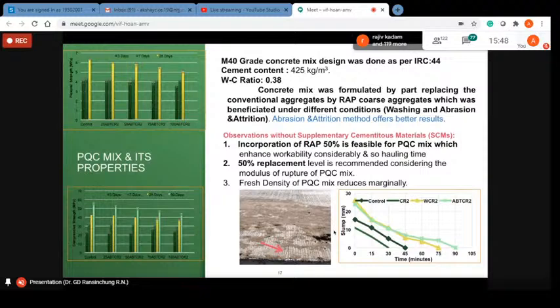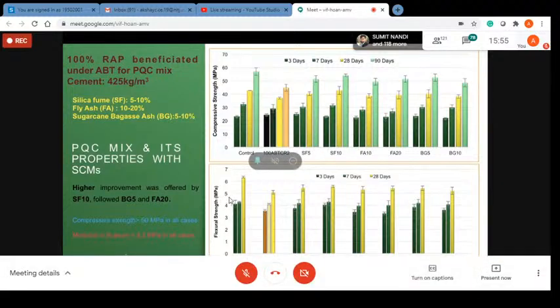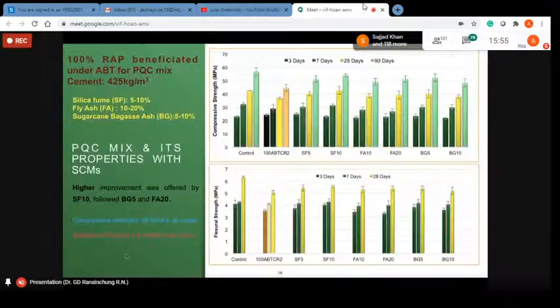crudes. Now, therefore, an attempt has been made to look at the mechanical properties of the hardened concrete by incorporating these different mineral additives. From this bar chart, we can see the details, but I would like to conclude here. Higher improvements in flexural strength as well as in compressive strength were offered by the mixed combinations having silica fume 10%, followed by bagasse ash 5% and fly ash 20% respectively.